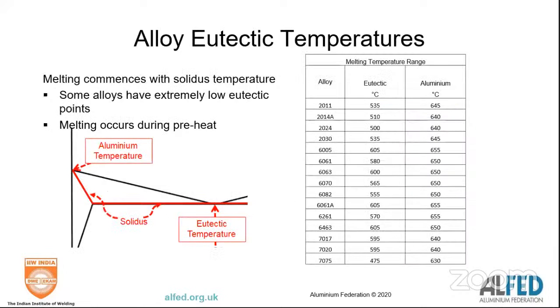And you come across the first problem, that the eutectic temperatures of particularly some alloys are extremely low. So you can actually get some melting during the preheat. You're not in the position to upset, but you can experience some melting in the preheat.